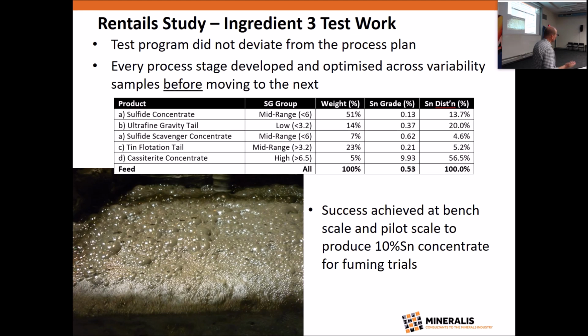So no matter what results we got from the early tests, and some of them were pretty average, we just didn't deviate from the test plan. And every process stage test was practiced to get the equipment and the conditions right, and then developed and optimised on variability samples. So there was always constant changing that we could track.